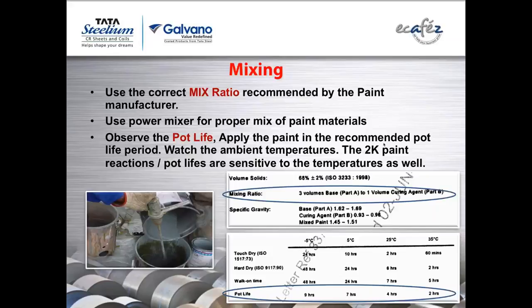So usually pot life in case of 2K paints, 2K stands for two component paints where base and hardener are different. Thinner is not considered as a component. The reaction is going to start and it is going to end. So normally in case of 2K paints, we say that whenever the viscosity of that paint is doubled, that threshold time is called the pot life. Before that, you have to apply the paint. Now, they will write 4 hours as pot life. Ideally, we have it 4 hours because it is half a shift, what you get till lunchtime.